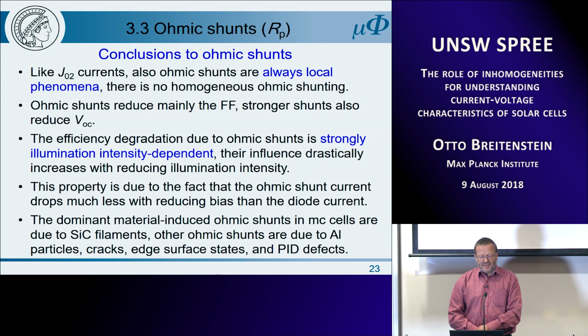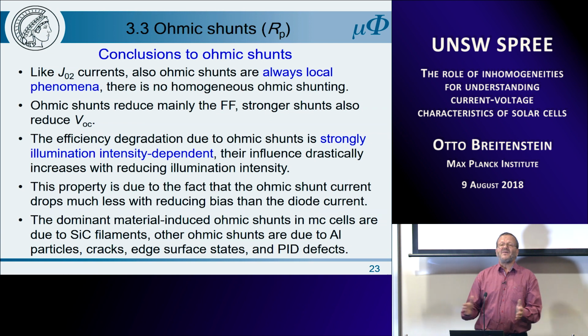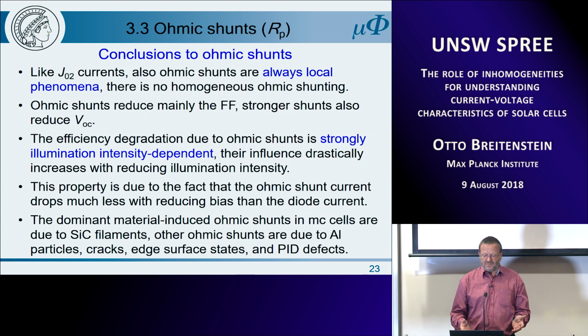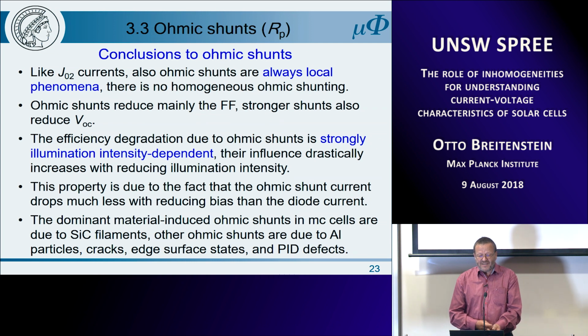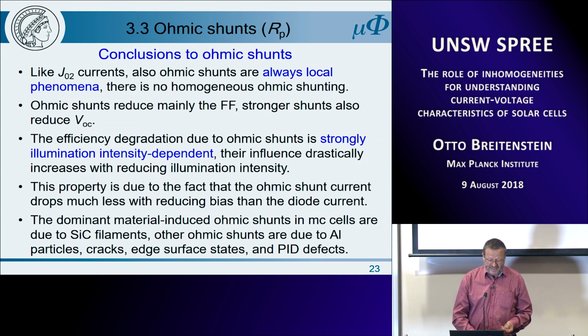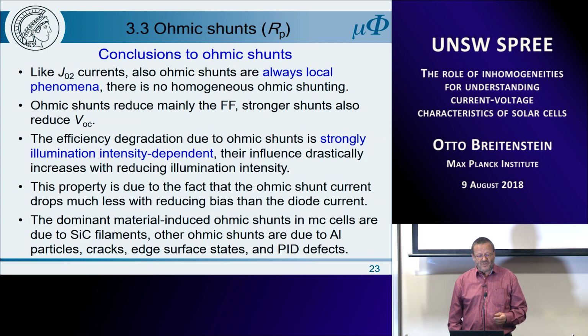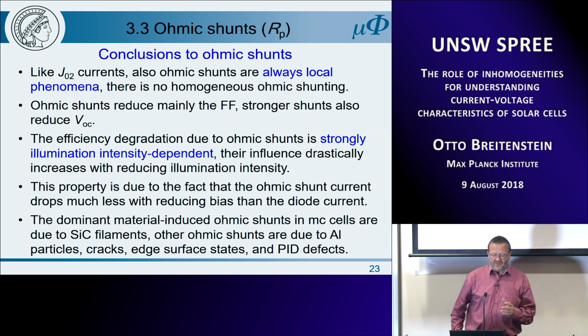And this property is stronger than in the case of J02 due to the fact that the ohmic shunt current drops much less with reduced bias than the diode current. The dominant diode current is still dominated by J01. And the dominant material-induced ohmic shunts in multicrystalline cells are due to these silicon carbide filaments. Other ohmic shunts are due to aluminum particles, cracks, edge surface states, and also PID defects.